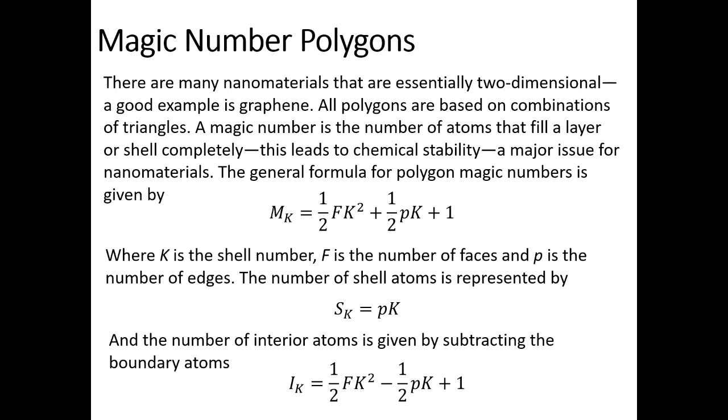But before we do that, it looks like I have a perfect place for one atom right there, right? Why isn't that atom a good atom? Well, if I put it there, first of all, it's not going to be a magic number. Secondly, it's not stable. This is 55 gold atoms. It happens to be very stable, relatively stable always. This would be 56. That doesn't work. If I do what's called mass spectrometry, it can measure the cluster. The cluster of 55 gold atoms is this strong signal, and the cluster of 56 is like here. It does exist briefly, but it's not stable. I can put atoms here, not stable. I can put one here, no, it doesn't work. This works. This is the 55 atoms.